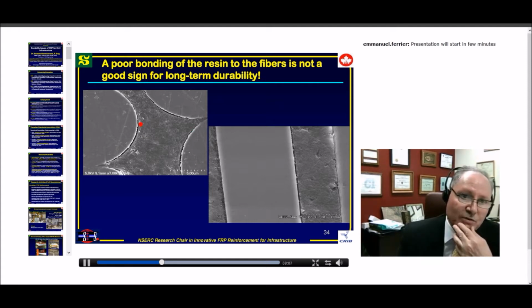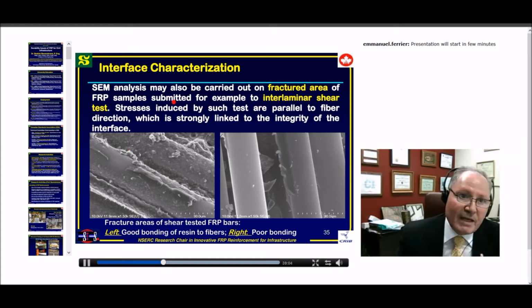Next, as you can see here, this is poor bonding. You can see here the gap. And this is, of course, before starting the investigation. I strongly recommend that when you are doing a durability investigation, you also do microsectional analysis on the material as received, before conditioning, because sometimes you can find a lot of defects and problems in the as-received material. If you do not do it and you start your investigation, you may come out with some wrong conclusion, because maybe the deterioration was in the as-received material. It was not really induced by the load or by the environment.